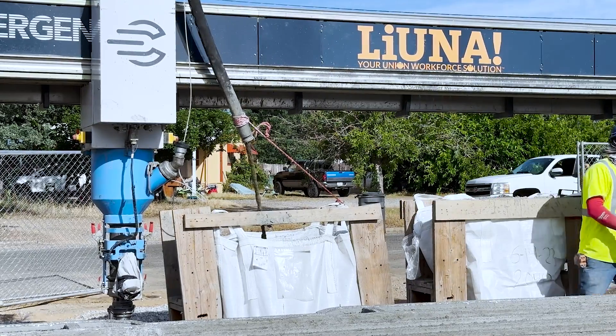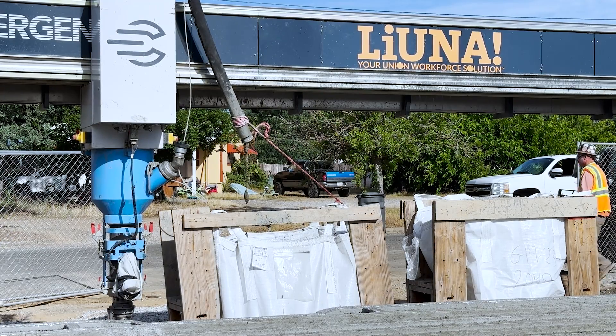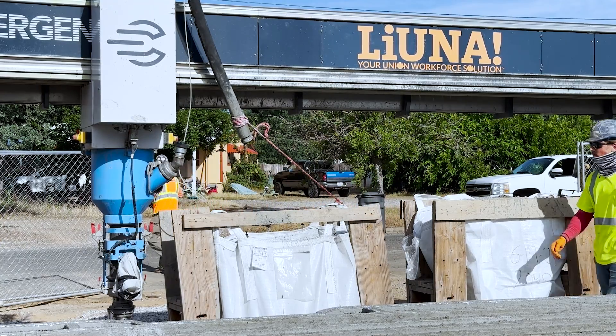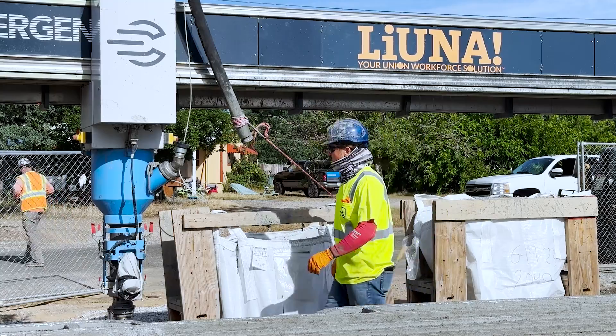Now the pressure is on for Sean — both literally the pressure in the hose and the pressure of the importance of this step on the job site. As the concrete reaches the appropriate hardness to support the next layer, if they go too quickly and the material is too wet, the concrete will slip off the old printed layers. And if they wait too long, they risk clogging the hose. This is the most critical component — getting the first layers of the day going, and then keeping it consistent from there.